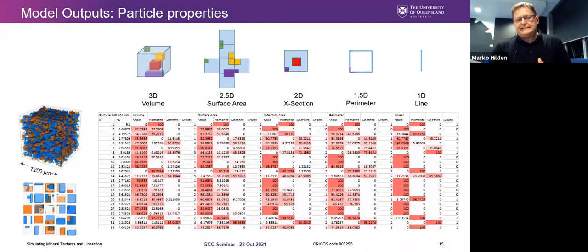One of the model outputs is a series of large tables that contain properties of each particle created. So if you're creating 10,000 particles per size class, there's a lot of information there. For each particle, you can calculate the density and then its composition by volume, by surface area, by 2D cross-section, by perimeter, by line. And this information might be useful in different contexts.